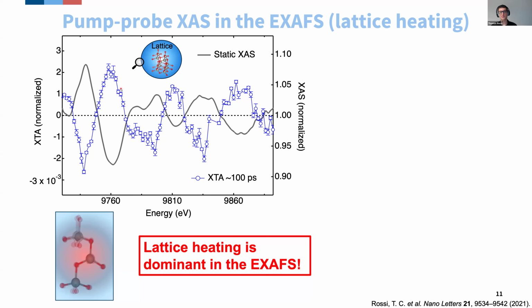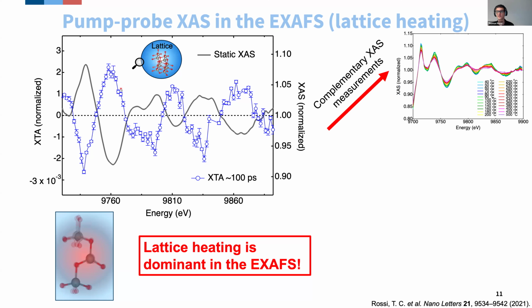And we can use this pump-probe signal in the EXAFS to tell by how much the lattice heats up. We have done this with two different techniques. One is by doing complementary X-ray absorption spectroscopy measurements, where we put the thin film on a heating stage and simply record X-ray absorption spectra at multiple lattice temperatures. This gives us a database.